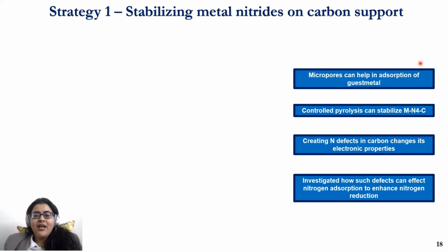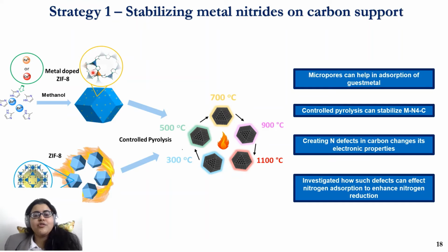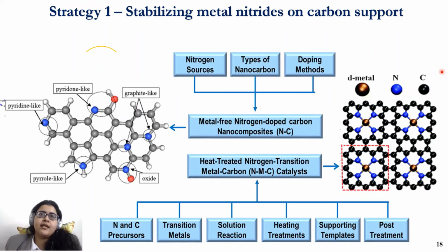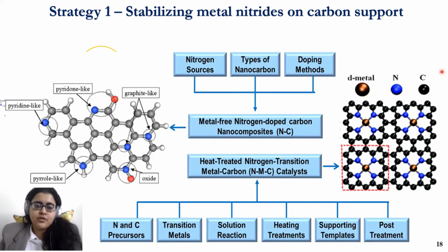So the idea was to use metal doped ZIF-8 and use controlled pyrolysis, try out different conditions under which we can create the defects, and then use those defects to see which will be better for nitrogen absorption and increasing the selectivity of nitrogen reduction over hydrogen evolution. There are different ways it can be done. You can take different types of nanocarbon, you can use different doping methods, there can be different nitrogen sources. Based on that, there would be different transition metal carbon catalysts, different types of reaction, different heating treatment. So all kinds of things that you can try out.